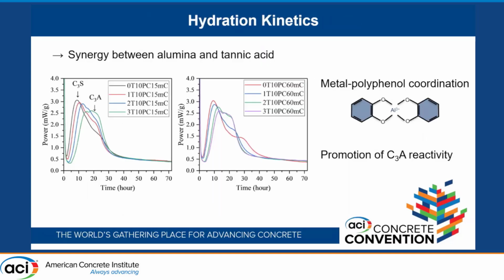And then here's another interesting aspect that we noticed with the use of tannic acid. Besides the synergy that we have between the alumina and the limestone, like we saw in LC3, tannic acid also shows some synergy with alumina. Through this calorimetry test, we could see that tannic acid is able to promote the C3A reactivity. This is mostly attributed to the metal polyphenol coordination, which is basically all of those aromatic rings interacting with the alumina present in the mix.